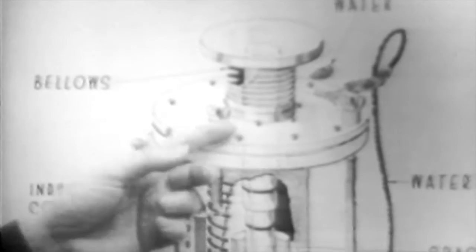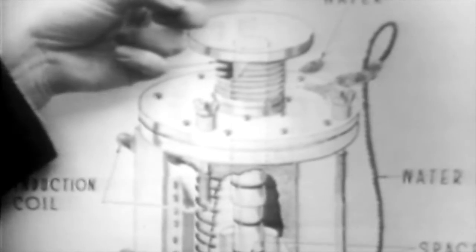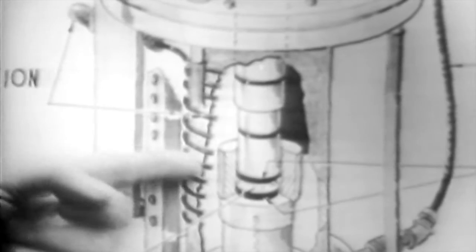Here you can see the individual components of a simpler model: the die, the plunger, the vacuum jacket, and the water-cooled top and bottom enclosures. Pressure is generated by means of the hydraulic ram and transmitted down through this plunger assembly, while high temperature is achieved by induction heating the die directly with a radio frequency coil.